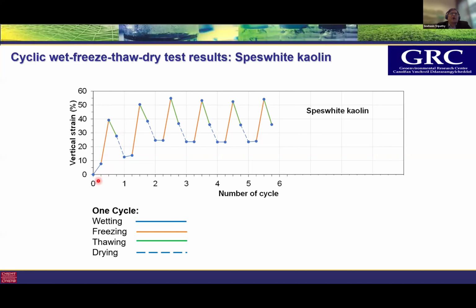The sample showed an upward trend of movement. So basically, the sample is gaining volume when it is taken through all these cycles. After a few cycles, as you can see, the top level and the bottom level kind of equilibrated. You can say that an equilibrium had been reached under these conditions. Note that one cycle is wetting, drying, freezing, and thawing, all together, and then the second cycle and the third cycle. So you've got a weathering pattern which is being imposed on the soil, and the response is shown there.